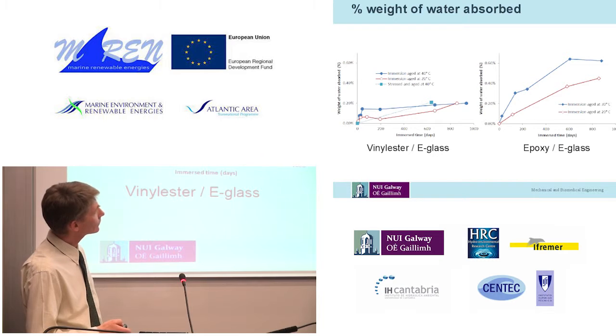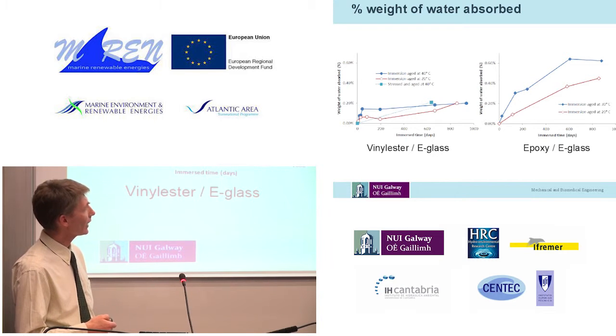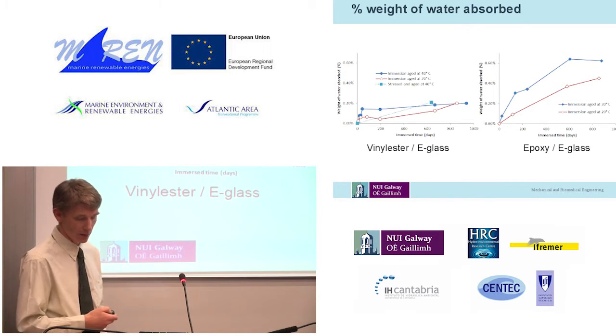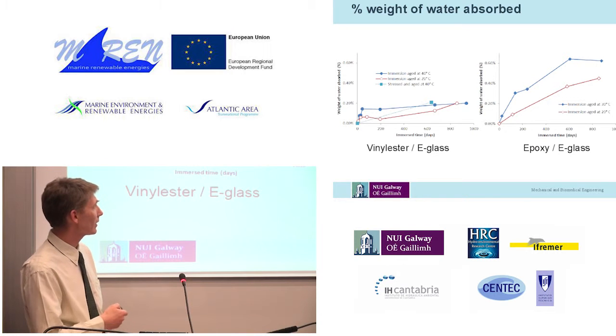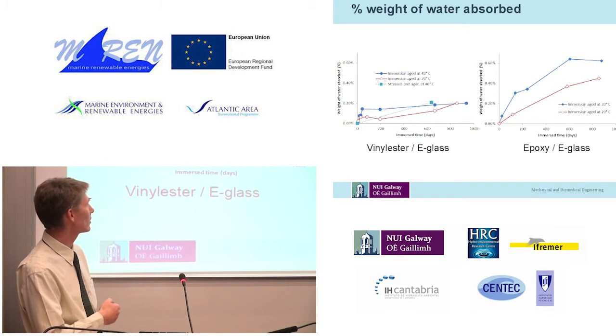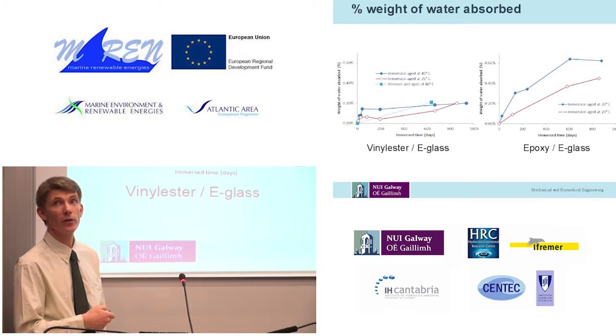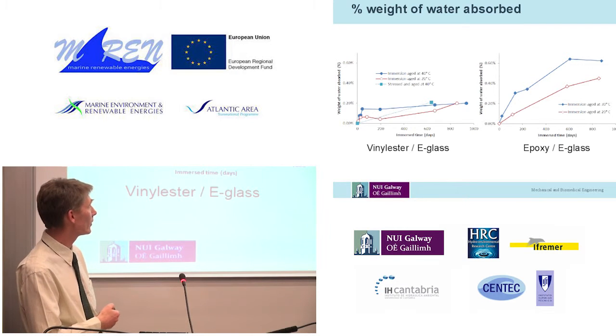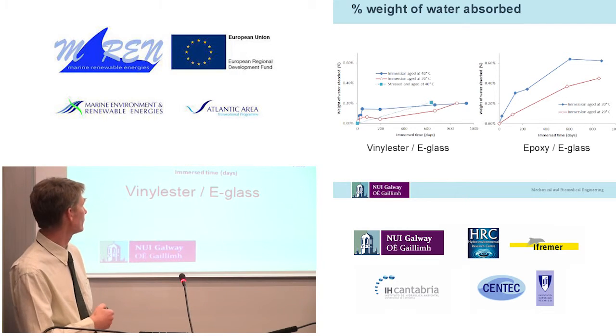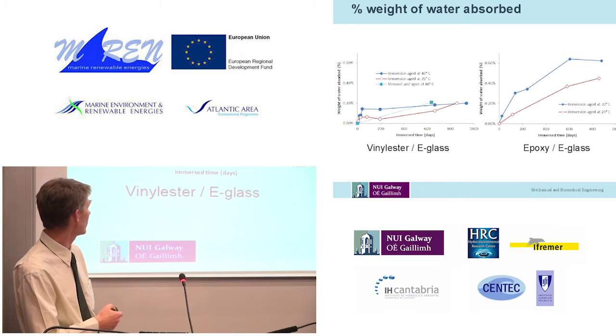Now, the reason for that, I think the main reason is probably that when I was looking for materials to use here, I chose materials that are specifically designed for water immersion. So the vinyl ester E-glass that I used was Scott Bader Crystic, and then the epoxy was Ampreg by Gurit.